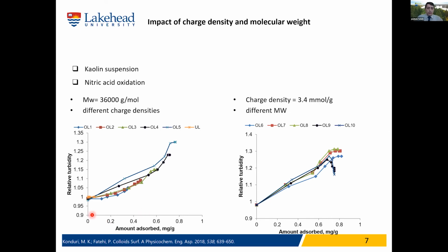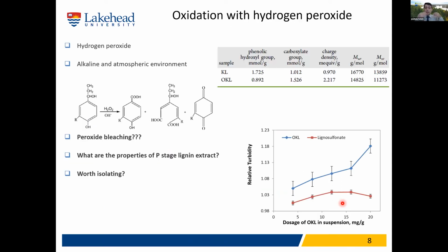What we noticed is that, first, by increasing the amount added to the solution, the adsorption would increase and the turbidity would increase. That's what we noticed in both batches. But if you look closer, here OL5 has higher charge density than OL1, and this is the order of increasing charge density. This is the order of increasing molecular weight. What we noticed is that the higher charge density samples generated better results. But for the molecular weight, at some point, it started to lose its efficiency. That's because when you have larger and larger molecules, they start to coagulate instead of disperse. So the higher the charge density, the stronger the repulsion, and that's a good thing. But with molecular weight, you need to be careful because you can't go beyond one level.